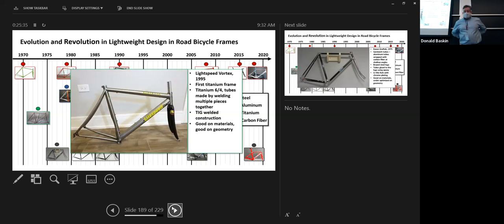The material, the 6-4 titanium, is too strong to form into tubes. So they actually bent these around a mandrel. Like they would take a sheet of it, roll it up, and then weld it along the seam. And they did a pretty good job of geometry here. You can see the tubes are, you know, this is both effects, right? This is materials and this is geometry.